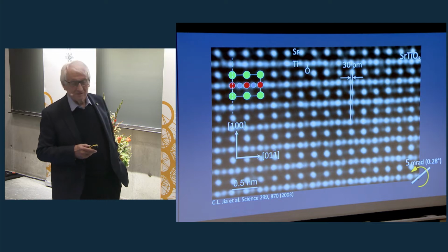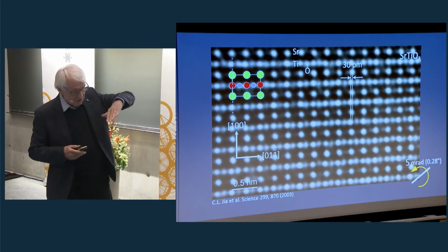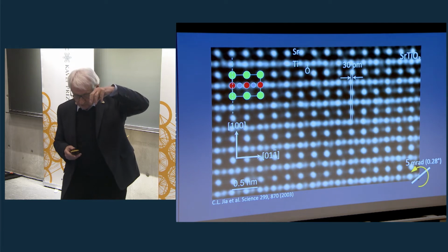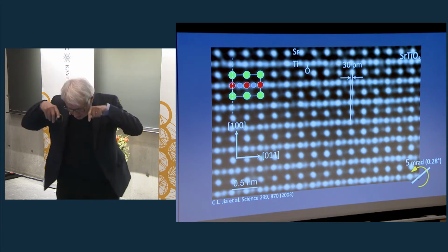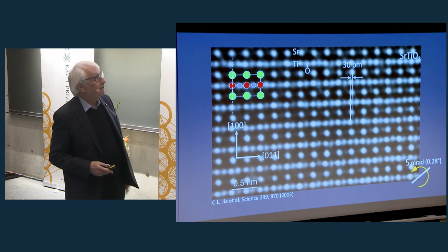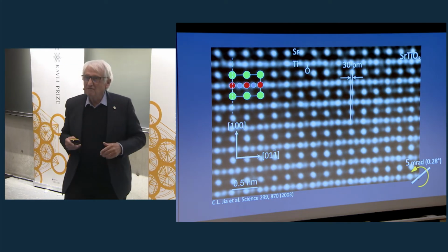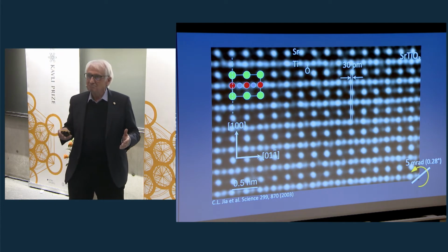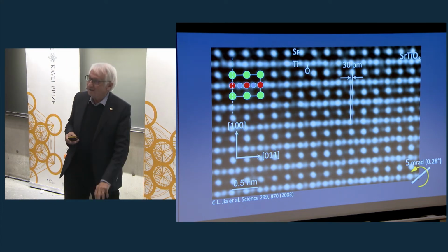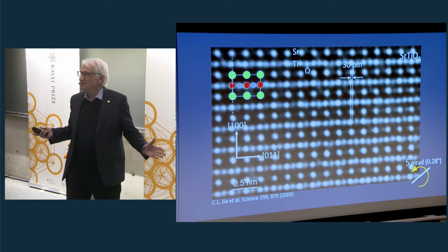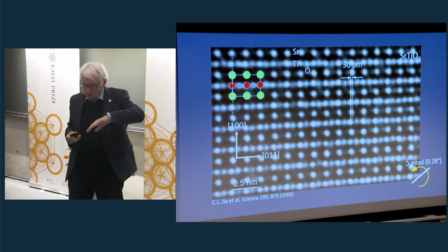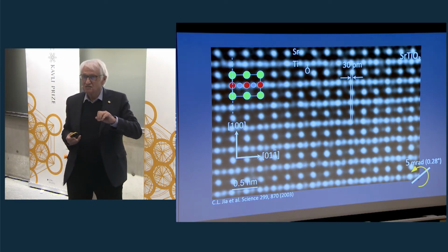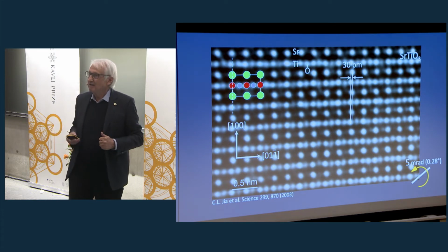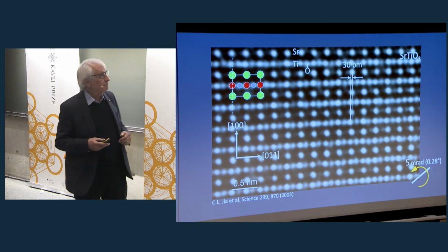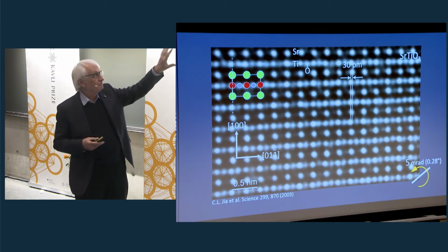The sample is tilted. Because I told you that you have to align the atomic rows in such a way that you can look along them. So you do that. But when you have in atomic dimensions some 10 up to 100 atoms to align perfectly, this does normally not work. You always have tilt in your samples, because we normally use a mechanical tilting device, and this is not arbitrarily correct, precise. Therefore, there's always some tilt in the samples.